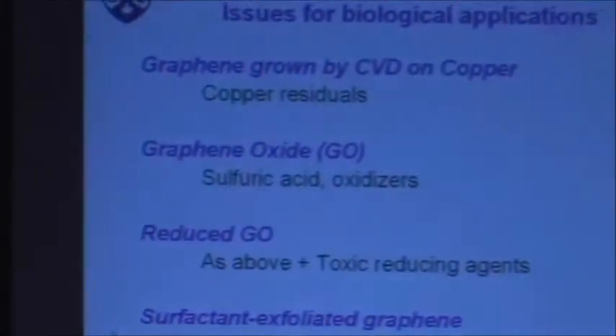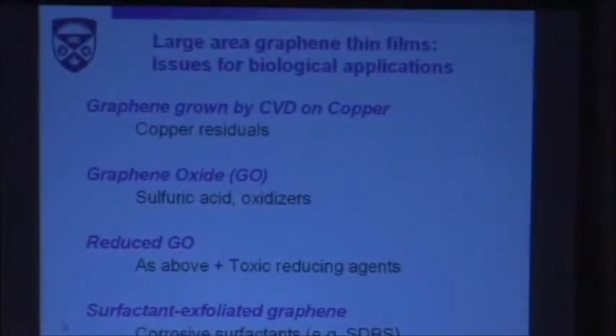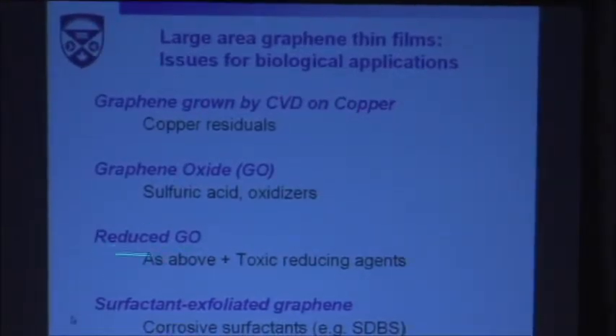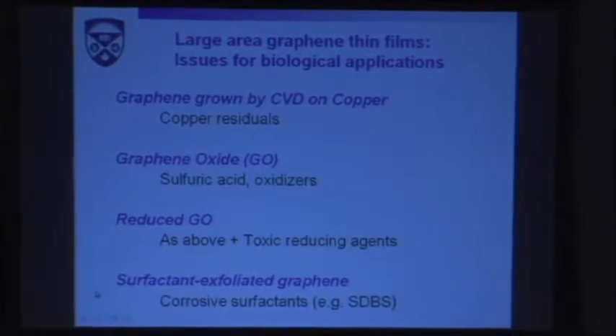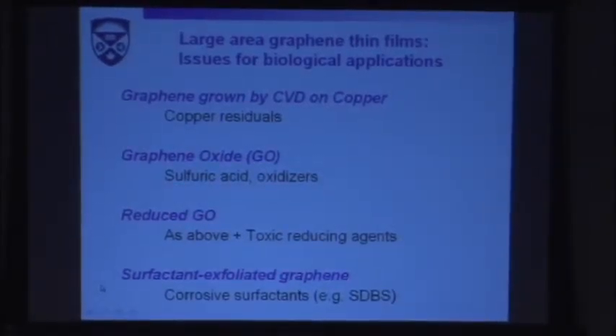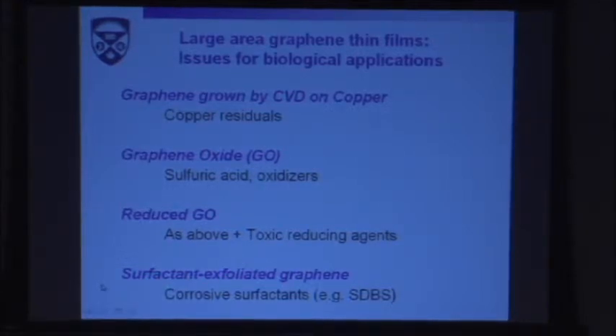They said immediately, no, graphene oxide doesn't work, because you put in nitric acid, sulfuric acid, potassium chlorate, corrosive things. Some of them will remain, and for the body that is not good. Think of something else, please, Giovanni. The other alternative is growing graphene by chemical vapor deposition on copper. That's possible, but copper residuals are also not nice to put in the body. Copper oxides are particularly weird. Reduced graphene oxide has the same problems as graphene oxide, and hydrazine is not something nice to put in the body, even worse. So again, it was about using surfactants that were biocompatible.